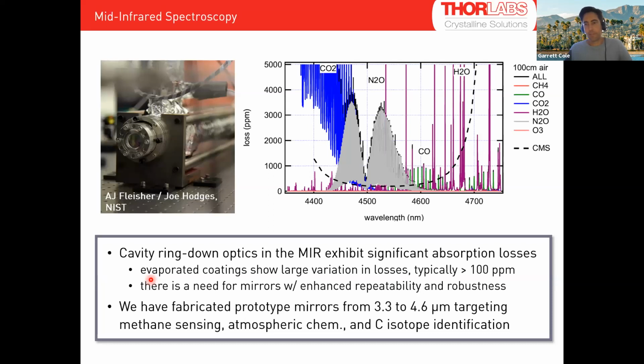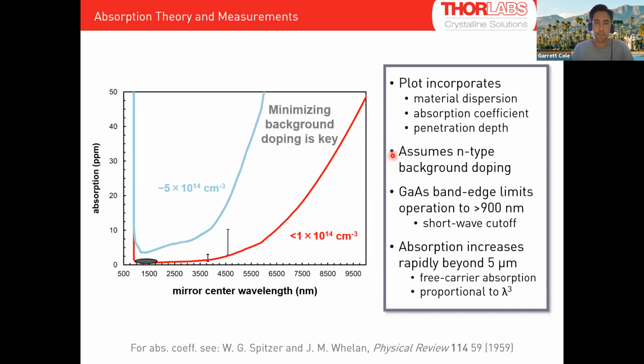But the mid-IR is obviously a very interesting space to operate. You have all these very nice absorption lines that you can access to do trace gas detection and so on. You can do really interesting spectroscopy on carbon-based materials, among others. And so this is what we're initially targeting: operation in the 3 to 5 micron range, making these long linear cavities for cavity ring down spectroscopy. For us, the key is to minimize background doping.